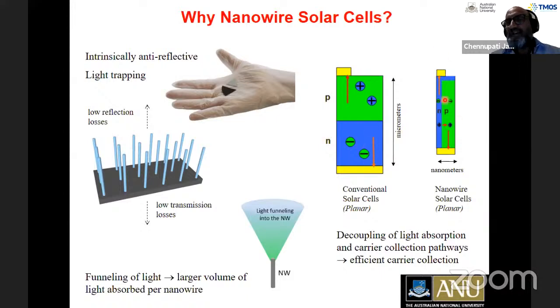But in the case of nanowires, you can make the nanowire as long as you want to absorb all the light. You can make a core-shell p-n junction, so thereby carriers can be collected efficiently. That means you're able to decouple the light absorption pathways and carrier collection pathways. Also, these nanowires can act like light funnels because of the high refractive index of the nanowires. Light always likes to be in the high refractive index medium, for example. They also have low reflection losses, so that means you don't need to put any anti-reflection coatings on them.